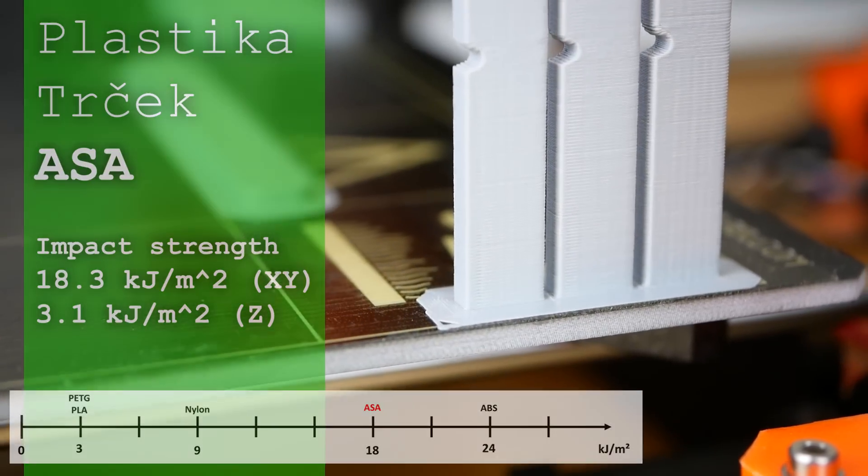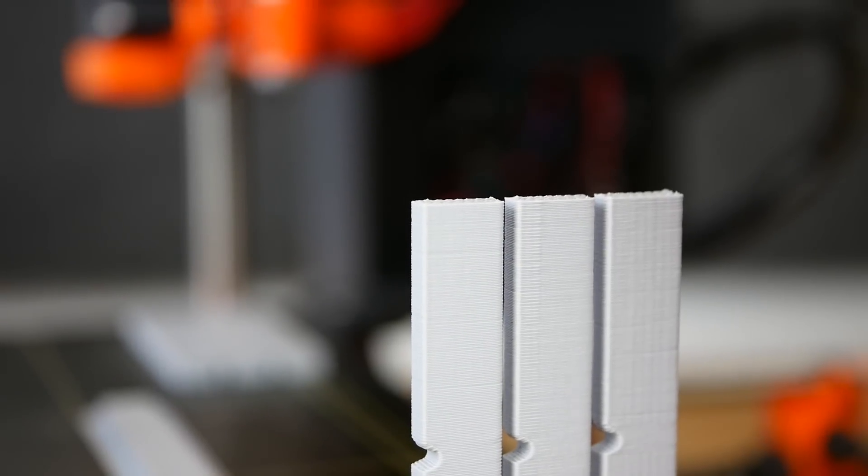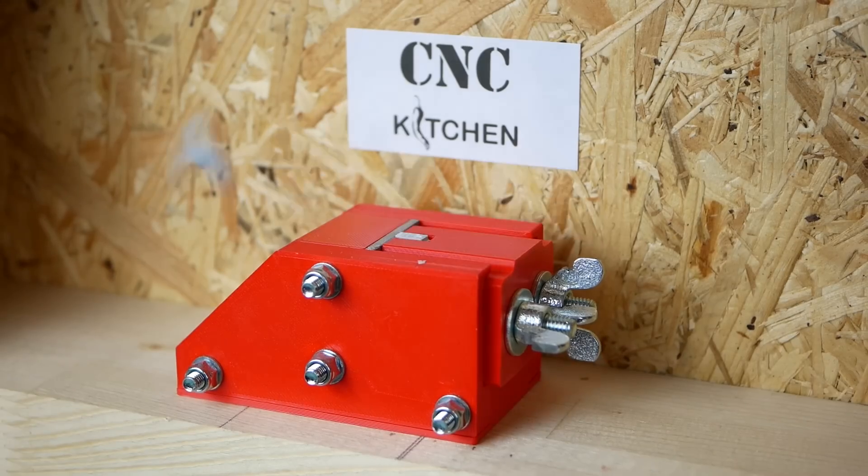With the standing specimens the layer adhesion problem popped up again and they were only able to absorb 5% of the hammers energy nicely breaking in between the layers.